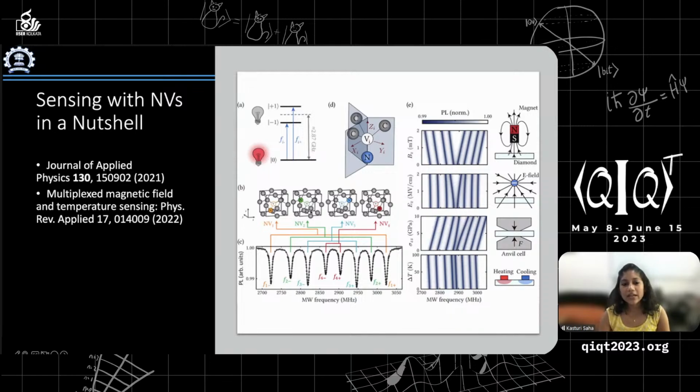But another interesting property of NV centers is that, remember, this is a diamond lattice, and therefore the nitrogen can be on any of these 4 locations, as you can see with the yellow, the green, blue, and the red location. The vacancies next to each other actually mark out different angles of the orientation of the NV center with respect to the diamond lattice. So it's along the 111 axis of the NV center. That allows us to measure different projections. If you have a field that is in an arbitrary direction with respect to your sample, you essentially will measure the projection of the field on the NV center axis, right?